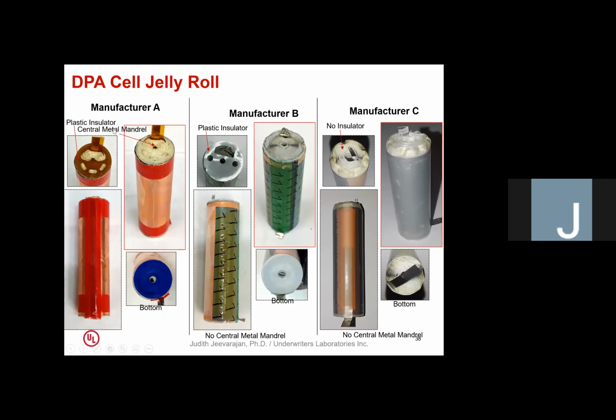But when we did a destructive analysis, what we found is manufacturer A, which is the original cell, has a central mandrel, and they also have plastic insulators on the top and bottom. With manufacturer B, we saw a plastic insulator. There was no metal mandrel in the middle, but it was quite flimsy. It wasn't like the one we saw in the manufacturer A cell. And we also did not see a bottom insulator. With manufacturer C, even the construction looks pretty bad. The way it's rolled up, you can see it's crushed on the top. No metal mandrel, no insulator on the top or the bottom.